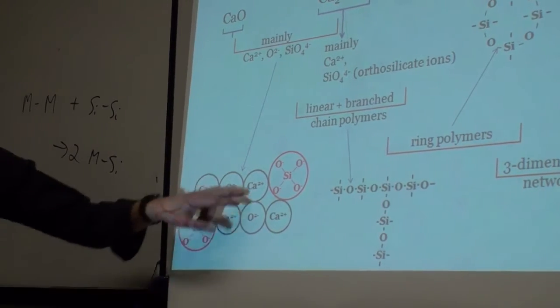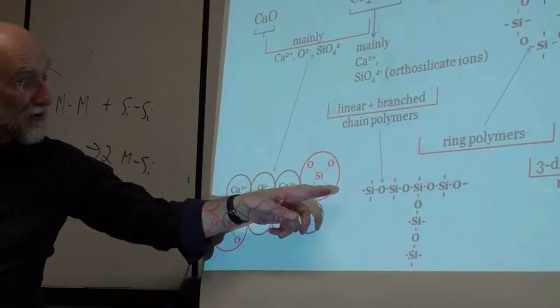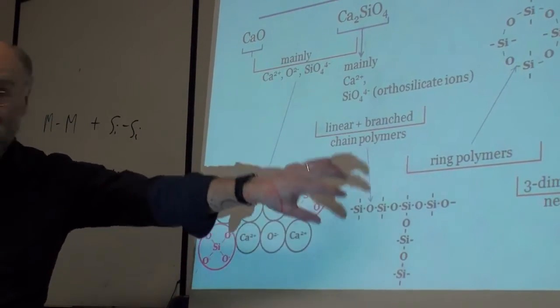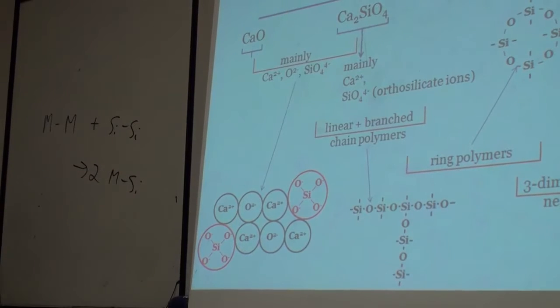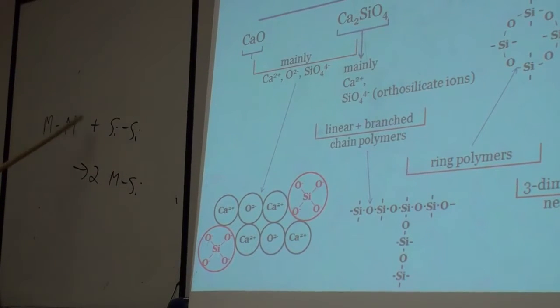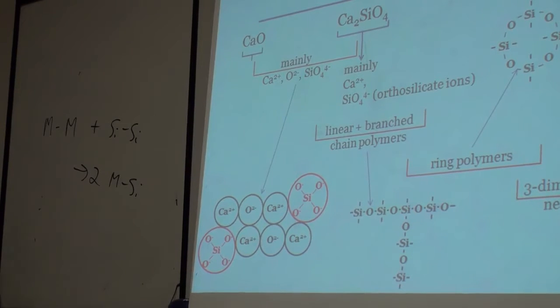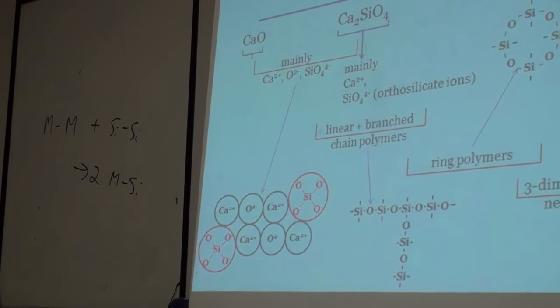Okay, but then if you start to get past Ca2SiO4, your complexes would have to share at least an oxygen, then you start getting dimers, and you start getting trimers. And as you get even further, probably the best way to treat it is simply to consider the second nearest neighbor and do it with the 1 sublattice quasi-chemical model, which is what we do.